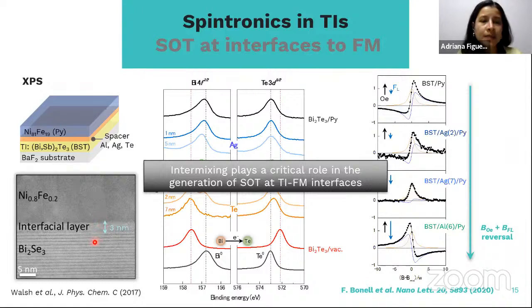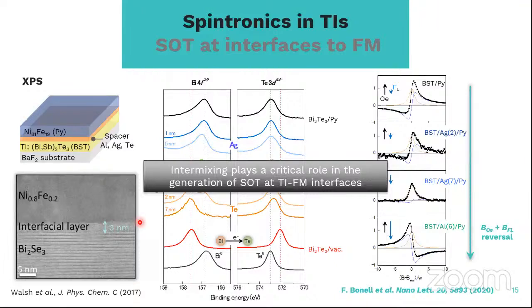So what we do is in fact to make sure to take into account that layer here, that is in this case, for example, reported to be 3 nanometers. But then when you use different kinds of interfaces, you are reducing such an intermixing layer or interfacial layer. So yeah, you take that into account. We made an estimation of that. Yeah, it's more like a value.